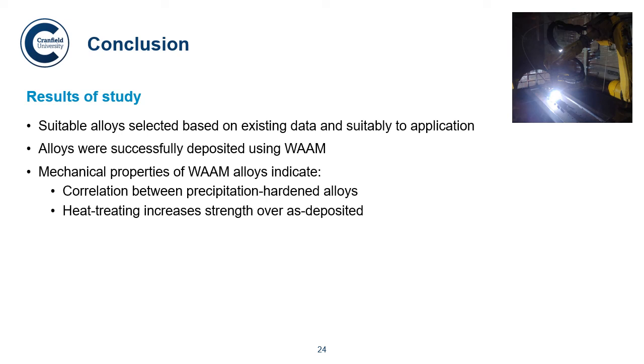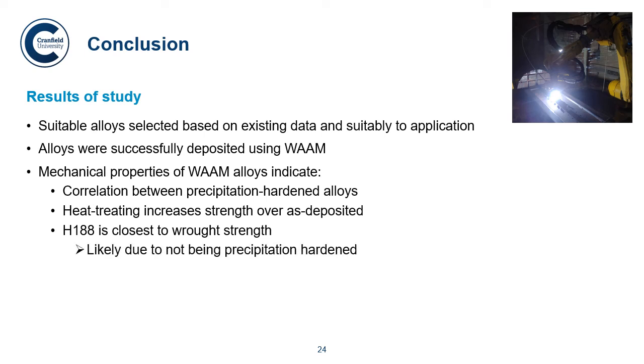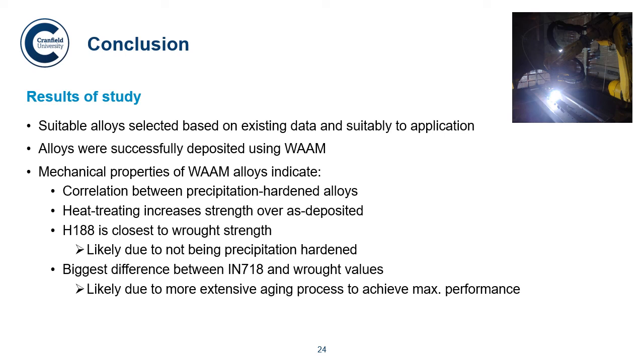Heat treating does increase the strength over as deposited material, and the biggest difference was seen in Inconel 718 and RE41. And H188 was the closest to the wrought strength, and we think that's likely due to it not being precipitation hardened. And the biggest difference we saw was between Inconel 718 and its maximum performance in the wrought data. And we think that's probably due to the more extensive aging process that 718 undergoes to achieve its maximum performance.